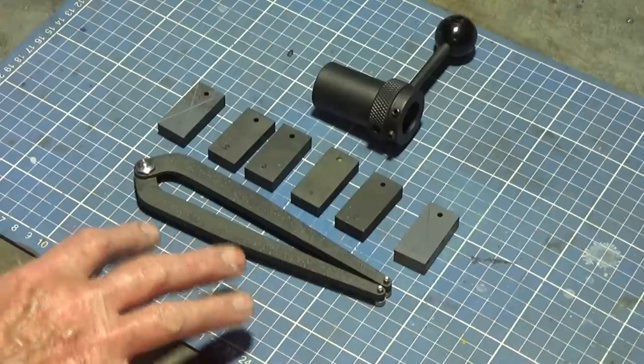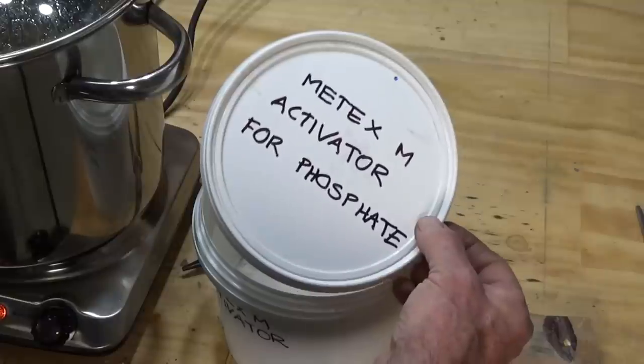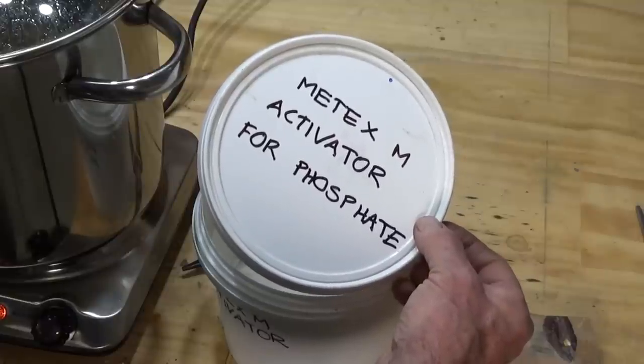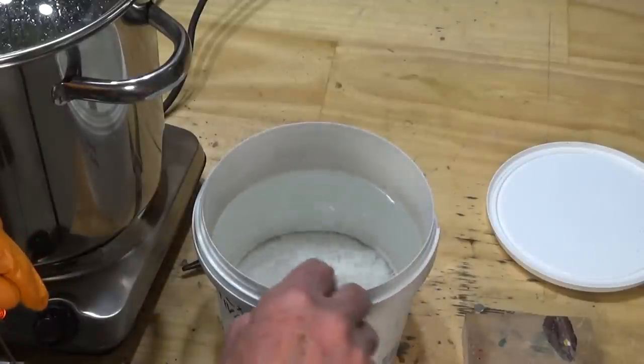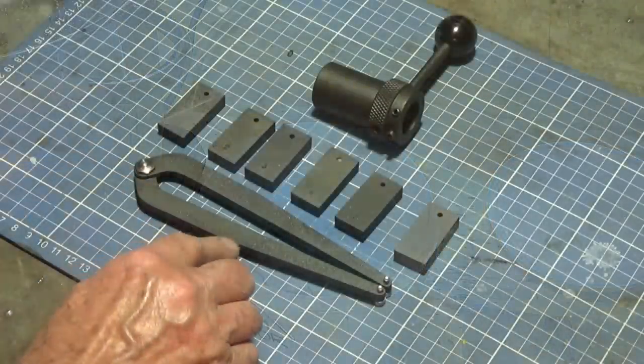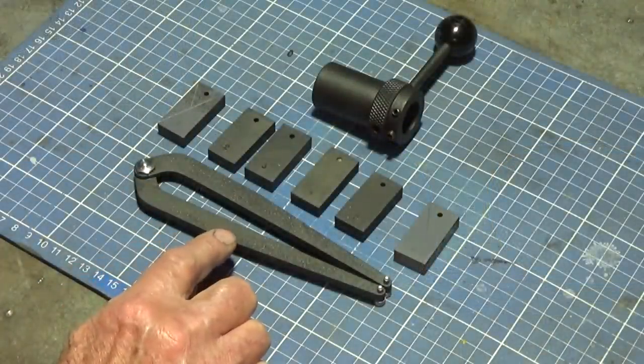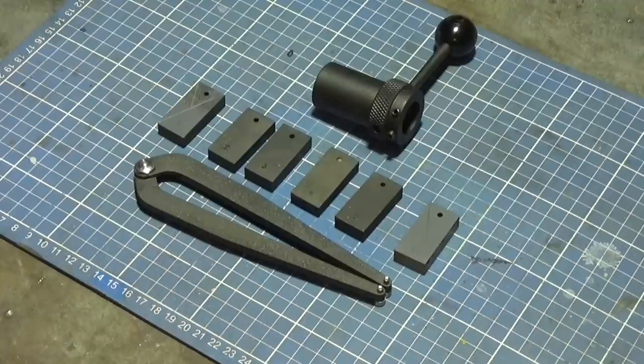The other interesting thing was that Metex M activator, which I thought was an acid solution, and I was wondering whether that was responsible for this crystalline effect in the phosphate coating. What they've told me is that the Metex M is not a phosphoric acid. It's a blend of acids that have been designed as a pretreatment metal acid activator. It is also used for different procedures when other concentrations, temperatures and exposure times vary for many other metal pickles, etc.